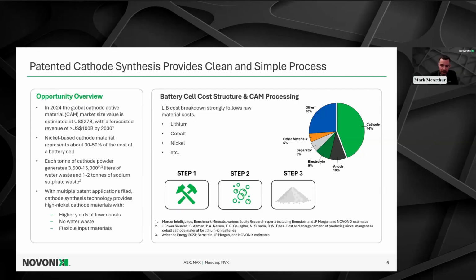What we do at NOVONIX is eliminate that second step. We are a precursor-free process to go directly from the raw material feed to a finished cathode active material. And this technology that we have developed since 2020 really offers higher yields at lower cost and doesn't generate any wastewater because you don't consume any water in the process to make the material. Also, we can use flexible input materials, which ends up being quite advantageous. And I'll get into a little bit of why on the next slide.